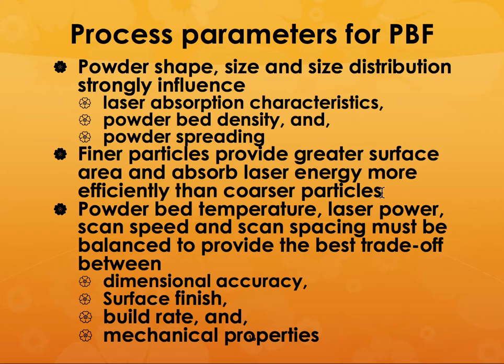Now, the powder shape, size and distribution can strongly influence the laser absorption characteristics, the powder bed density and the powder spreading. So if you have finer particles, it gives you greater surface area, but you remember this, finer metal particles are extremely pyrophoric. What does pyrophoric mean? Pyrophoric means it can catch fire. So you got to be extremely careful, and you are hitting it with a laser. So the inside of your envelope has to be in an inert atmosphere so that the powders do not catch fire, powders do not get oxidized and so on.